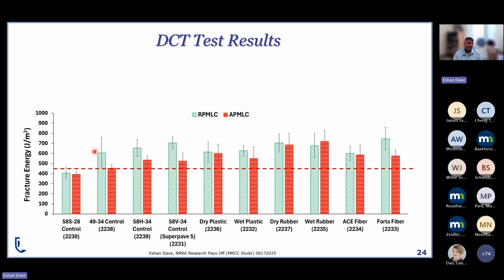And as expected, after aging, most of them saw a drop in that as well, with the only different ones being the ones with the rubber. So from a low temperature perspective, it seemed that these mixes with rubber were really retaining their ability to absorb the energy even after having gone through aging, as opposed to other mixtures which were seeing almost a steady decline as they go through the aging condition.